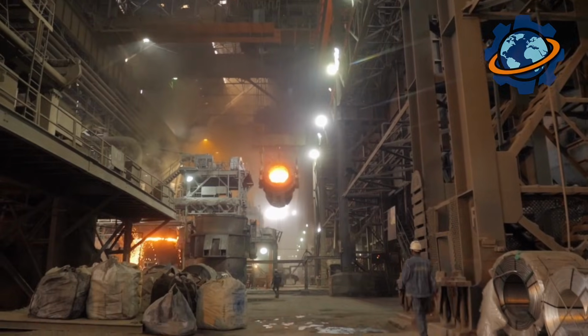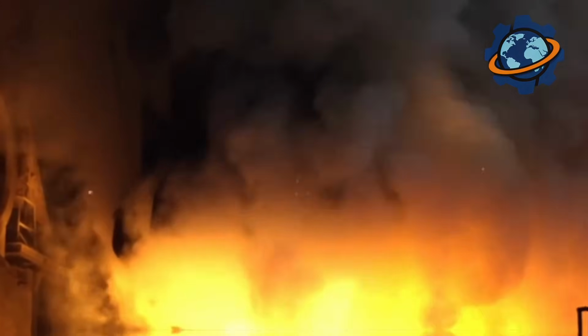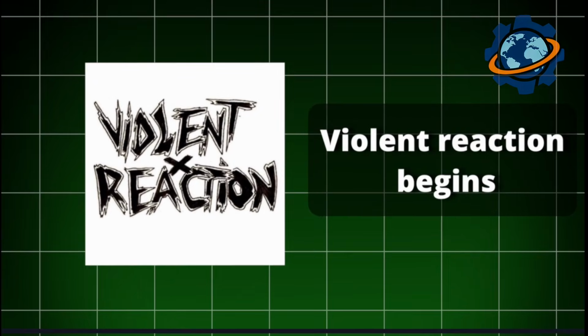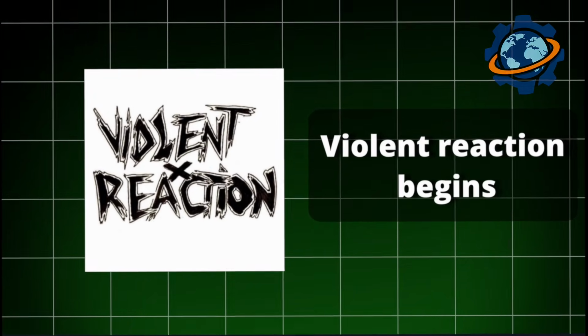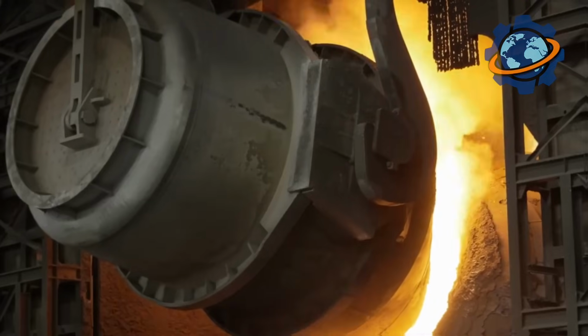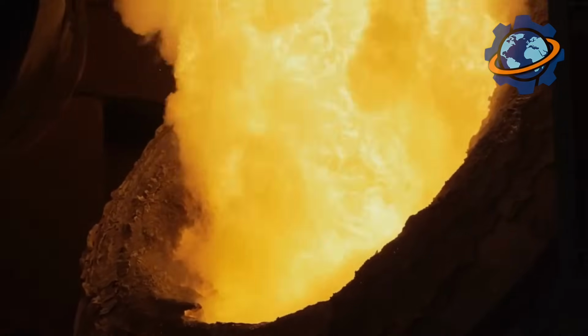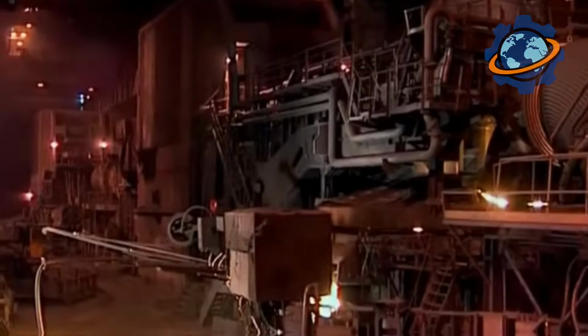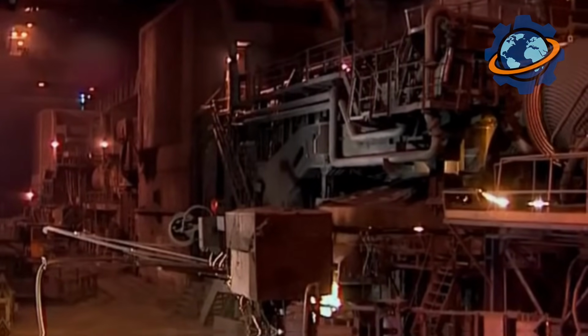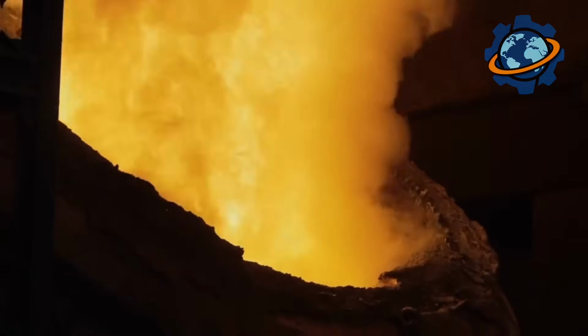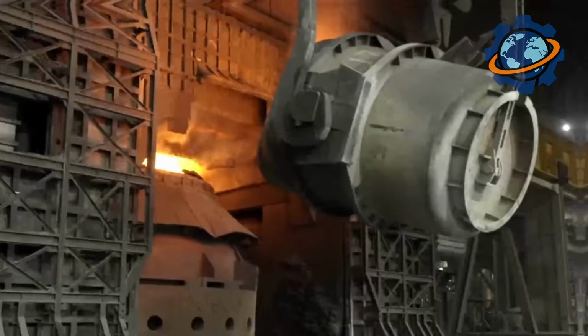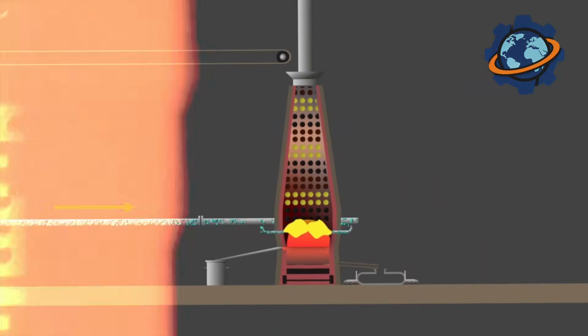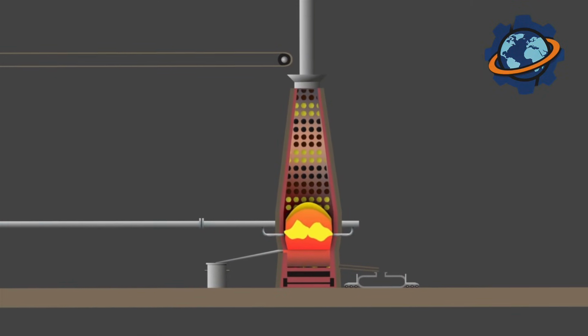Oxygen flow begins. A jet of pure oxygen at 150 pounds per square inch pressure strikes the molten metal. Violent reaction begins. Oxygen oxidizes carbon, silicon, manganese, impurities in pig iron. These exothermic reactions release enormous heat. Temperature rockets to 3,200 degrees Fahrenheit. Metal boils and churns. Flame tongues several feet high shoot from the converter mouth.